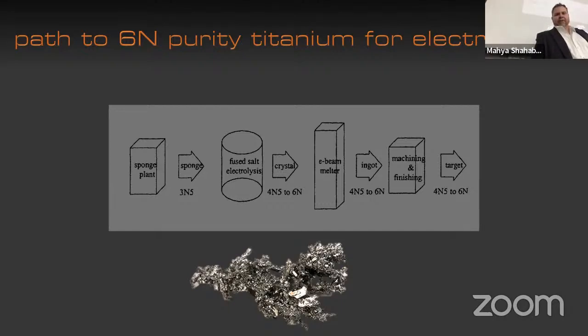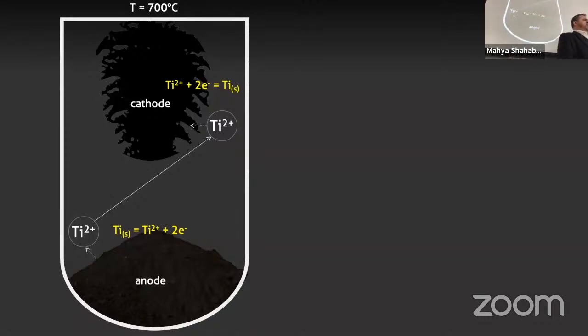microelectronics industry. Now, zooming in a little bit on the electrochemistry. This process operates at high temperature, because the electrolyte, sodium chloride and potassium chloride, is at its eutectic temperature with a little bit of superheat. We have this pot, and we're dumping in the sponge, which looks like little pellets, little rocks of titanium, obviously porous, hence the sponge. You dump that into the bottom, with the salt melted on top. You'd also have a step where you chlorinate, sparging TiCl4 in, to get the concentration of titanium in your electrolyte to the right ratio.